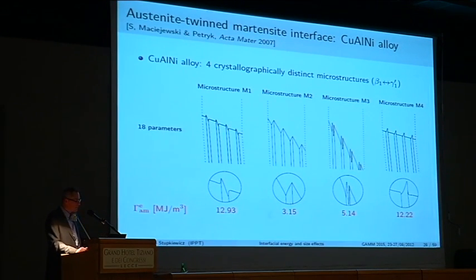So these are the results for copper, aluminium, nickel alloy, and in this material there are four crystallographically distinct microstructures. This is a cubic to orthorhombic transformation, and these are the results. So here you see the morphology of the interface, a close look, and the numbers. Okay, numbers are not of much interest, but we can use them in our modeling, so we have input for our modeling.